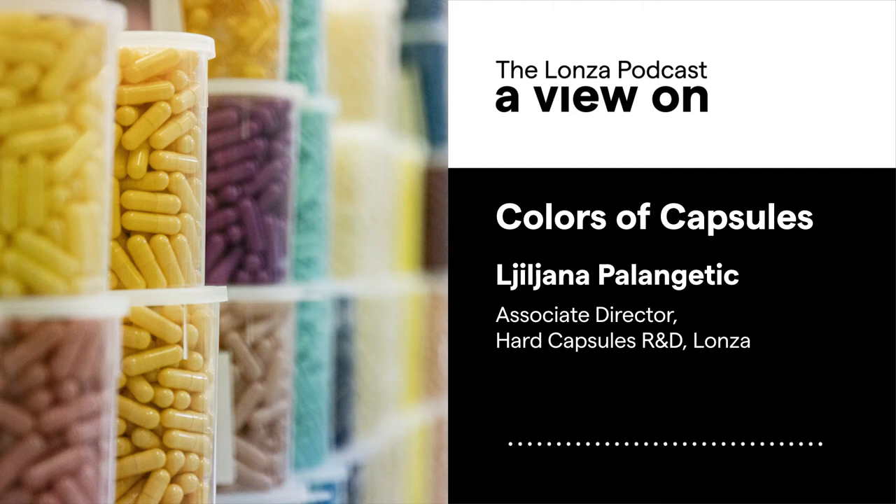If I may ask, what dye or colorant additive is used instead of TiO2 to ensure the whiteness? We stayed on the list of additives, but these are not necessarily listed as colorants — rather as pH adjusters, soluble salts, and so on. By combining the properties of the gelatin and the salt and the drying process, we managed to get really nice capsules. How does the white color actually arise? Basically the gelatin and the salts don't really like each other — once the drying process starts and drying progresses, they start separating, which leads to salt crystallization, which then results in this nice white color. So that means we will have white capsules in Europe in a few years? Yes — at least for gelatin.